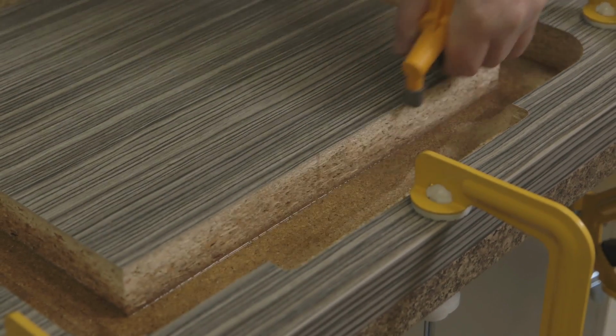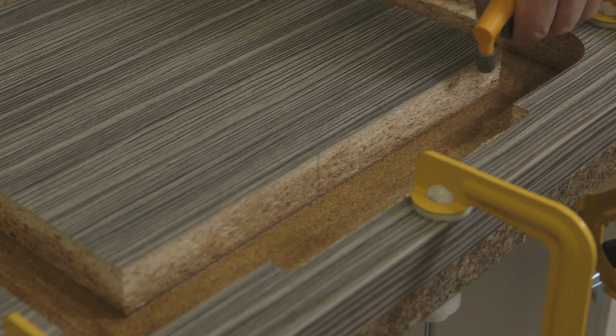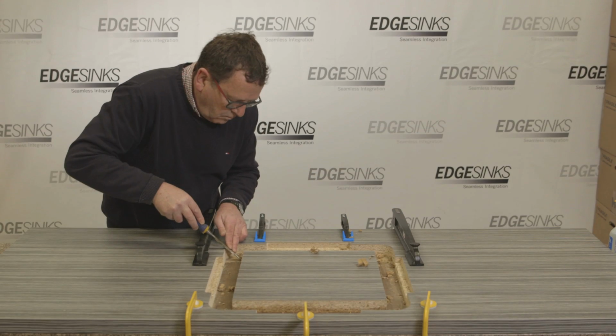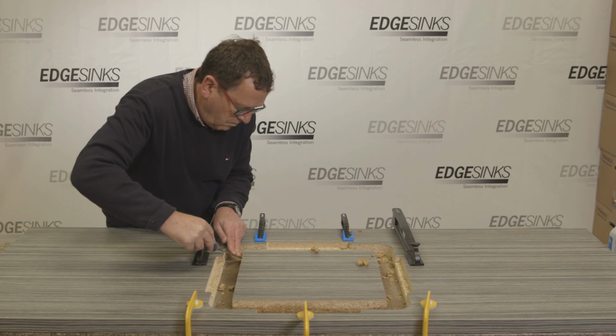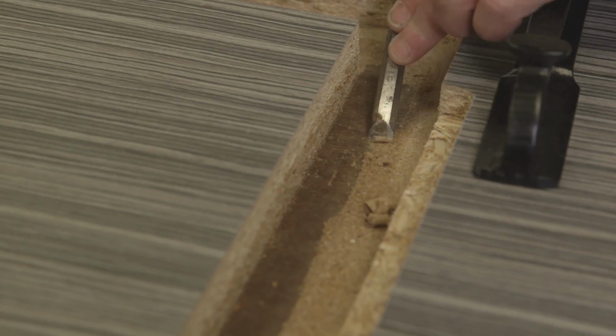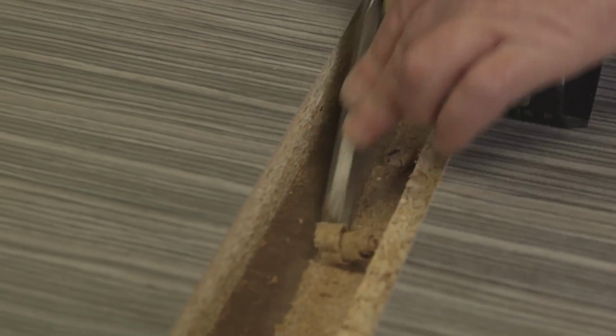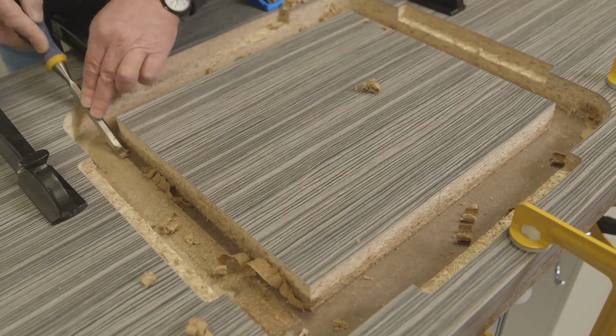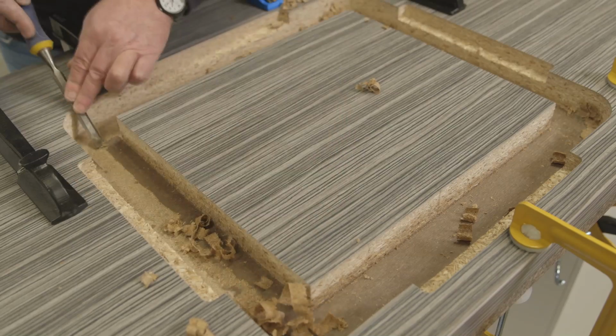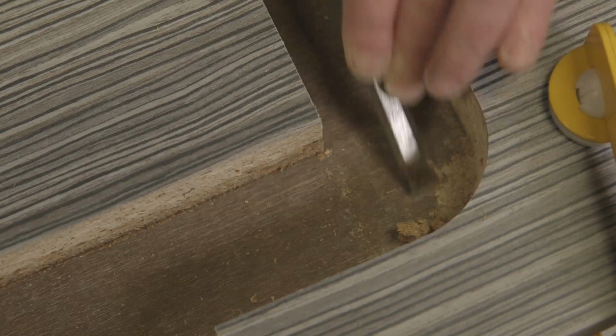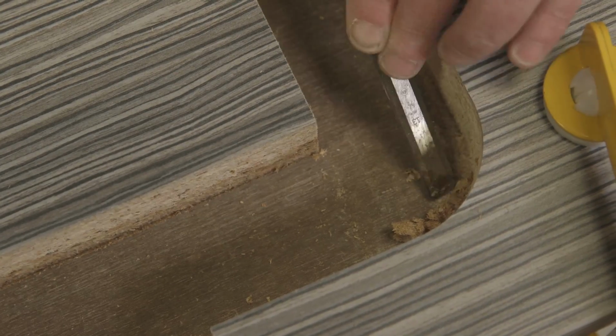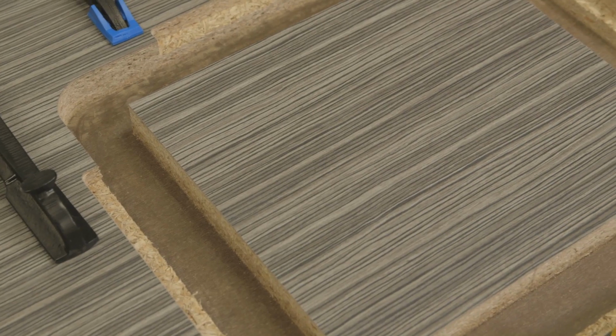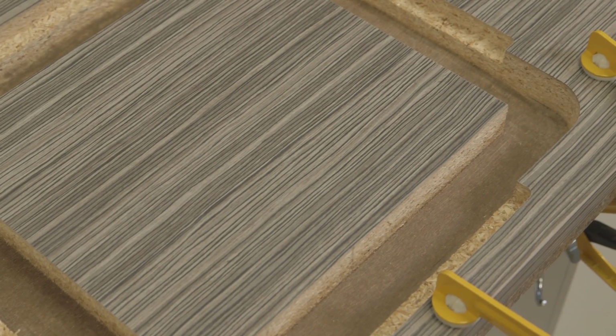Avoid letting the solvent soak into the outer edge, as this can cause delamination or swell the worktop. After a few minutes, the solvent will have softened the adhesive on the back of the laminate, and removing the excess particle board becomes easy. Remove the excess particle board using a wood chisel. Worktop manufacturers use various adhesives, so the penetration time may vary.